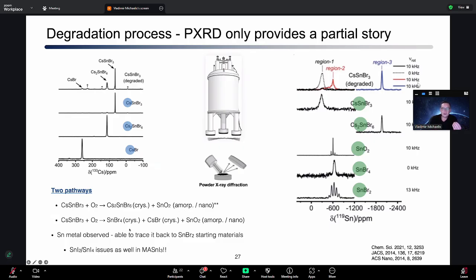You have to be really, really careful again of the materials you source. Just like I hinted to when we did the iodide phase here, where you get this mixture of tin 4+, tin 2+. If you buy tin 2 bromide from a variety of suppliers, what ends up happening is you have a metal impurity. And because these are made through high temperature processes, that metal impurity persists throughout the whole system. And that's what's actually giving rise to the metal peak, not the fact that it's basically reducing to tin metal.